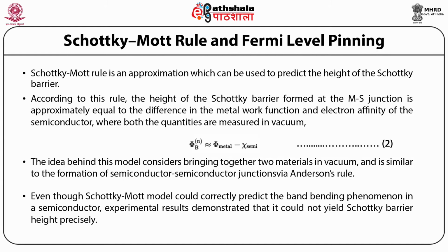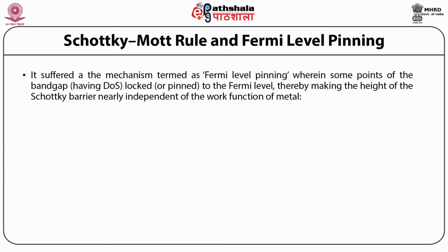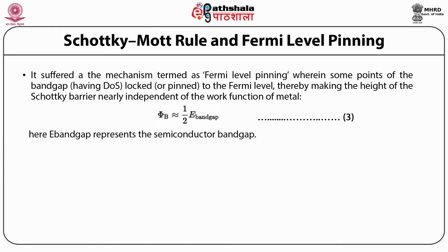Even though the Schottky-Mott model could correctly predict the band bending phenomena in semiconductors, experimental results demonstrate that it could not yield the Schottky barrier height precisely. It suffered from a mechanism termed Fermi level pinning, wherein some points of the band gap having DOS are locked or pinned to the Fermi level, thereby making the height of the Schottky barrier nearly independent of the work function of the metal. Here, phi_b is equivalent to 1/2 times E_bandgap. Here, E_bandgap represents the semiconductor band gap, and the above equation is represented as equation 3.